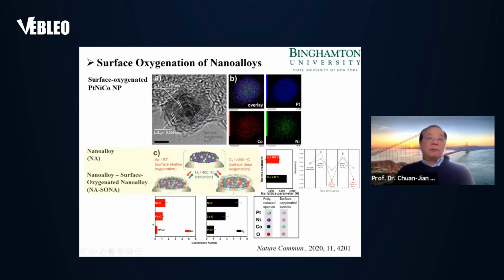Now, the bottom panel illustrates the metal oxygen coordination. One of the things I want to highlight is the oxyphilic metals such as nickel and cobalt. They basically take the responsibility of oxygenation, minimizing the oxygenation of platinum. That's really one of the important things for this particular nanoalloy structure. The oxyphilic metals take the responsibility of oxygenation rather than oxidizing the noble metal. That's very important in many catalytic reactions because we rely on the reduced state of noble metals.